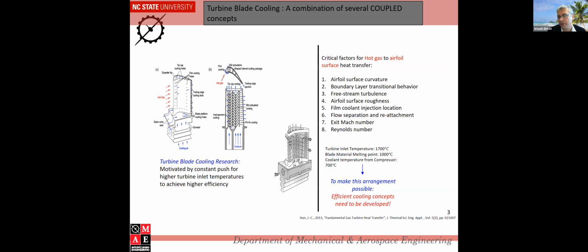In addition to that, the air coming out of the combustor, which hits the blade, is also heavily turbulent. You're looking at upwards of 15 to 20% free stream turbulence. And then because you coat the surface with TBC, it tends to make it slightly rougher. And when it's rough, heat transfer enhances. Then of course you have these holes in the middle, which tend to trip your boundary layer. That means you get a higher heat transfer coefficient right behind the holes. Then you get flow separation and reattachment, which could occur at